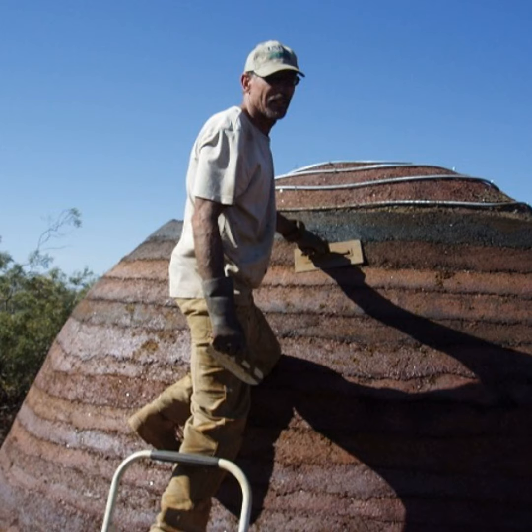I looked at my old silica fume, and it was yellow instead of snow white like it is when it's fresh. It had absorbed so much CO2 that it had changed color, and that was what it was bringing to the iron and reacting with it. It wasn't the silica itself, it was what it was carrying, which was all that CO2. And that's when I understood, oh, iron in water combining with CO2 has a strong reaction, forms this very strong product. And that's when I thought it might be a cement.